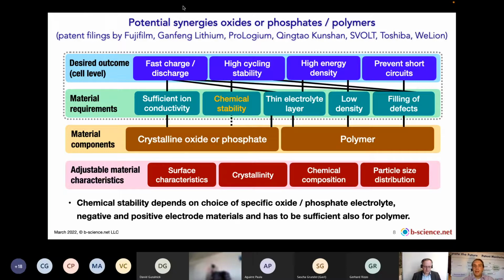On the other hand, making a thin electrolyte layer is very important too for several reasons: energy density, fast charge, discharge. And this is quite well possible by combining polymers with oxides. It's quite similar to what is often done in the coatings industry of using inorganic fillers with polymers that have a binding function to have thin films. So this is an area with synergies.